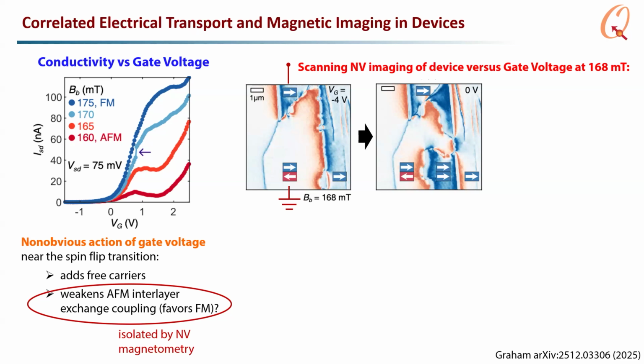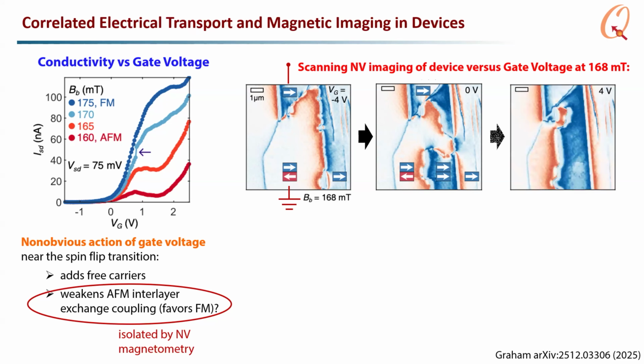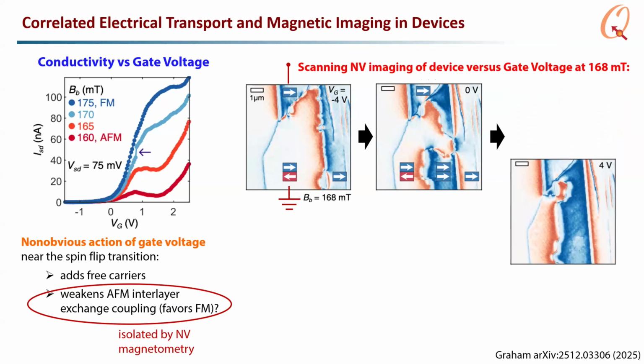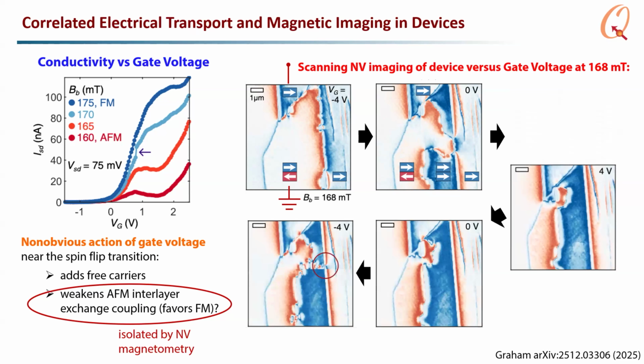sit at a single magnetic field and do the imaging. And by doing the imaging, I can isolate changes in the magnetic state as a function of the gate voltage. And what I see is that as I increase the gate voltage, the ferromagnetic domains start to slide across the bilayer. Okay, so this is another effect that increases the conductance.